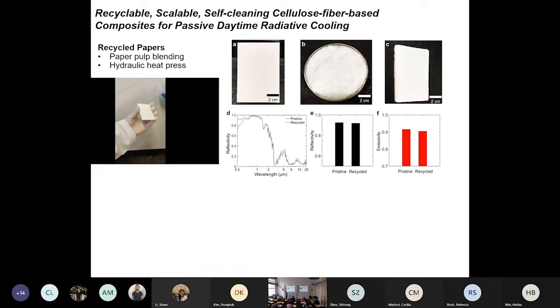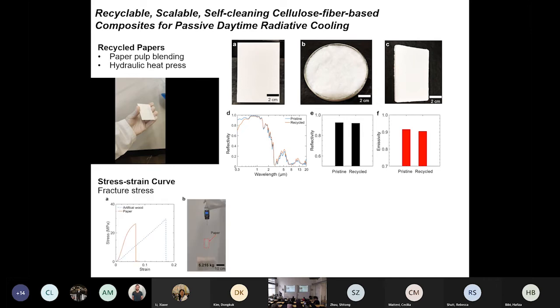So we really made the paper using the recycled paper, and then we measured the reflectance of visible light and emissivity for infrared light of interest here. As you can see here, almost the same. So recyclability does not actually compromise the expected cooling performance. So this is something I want to show you.